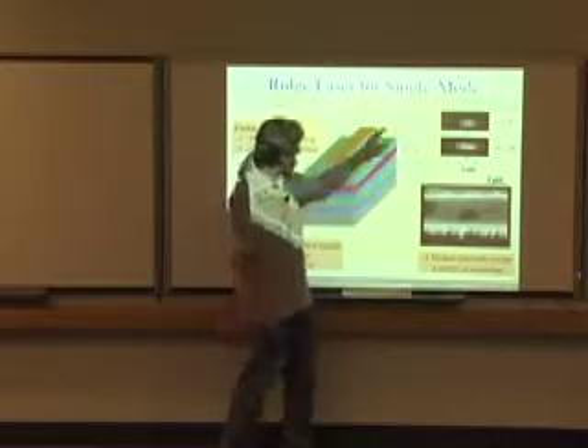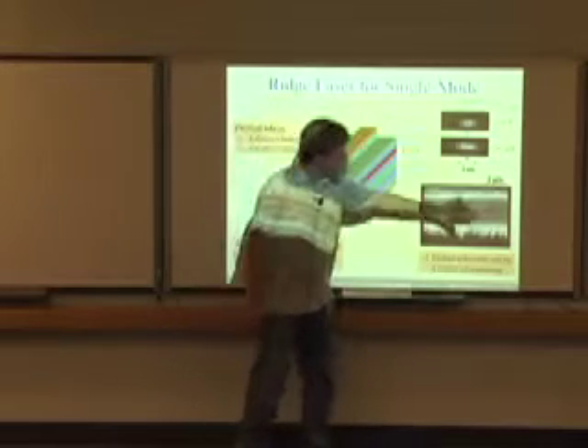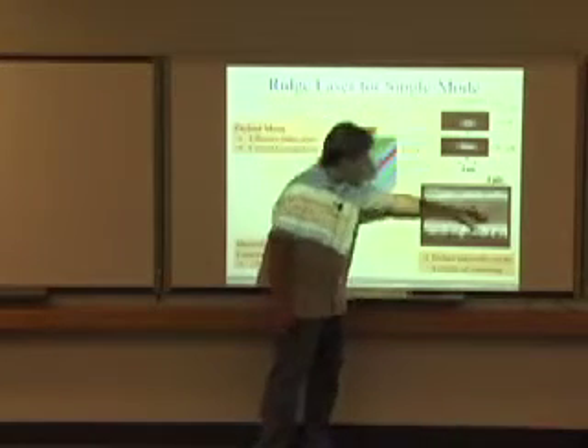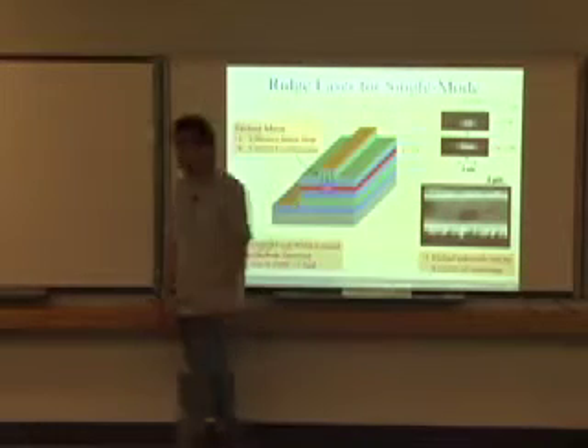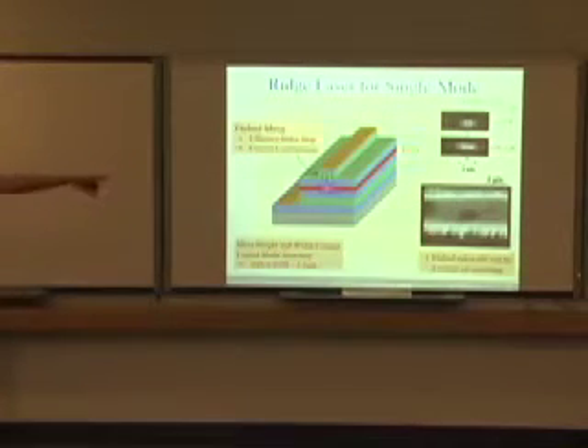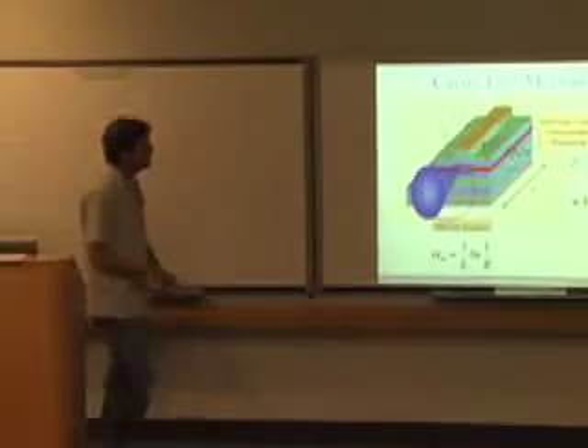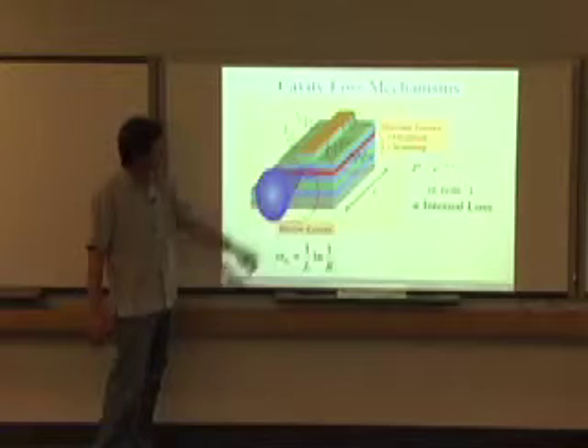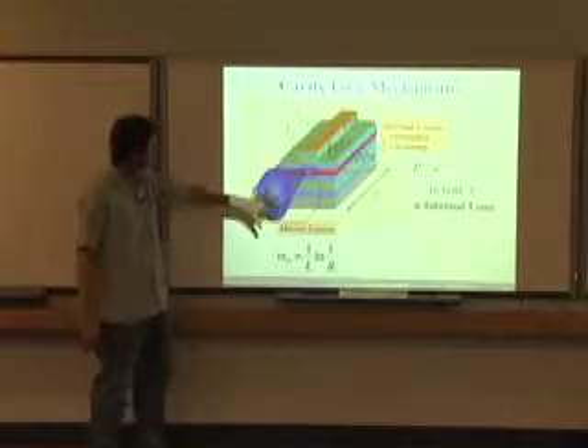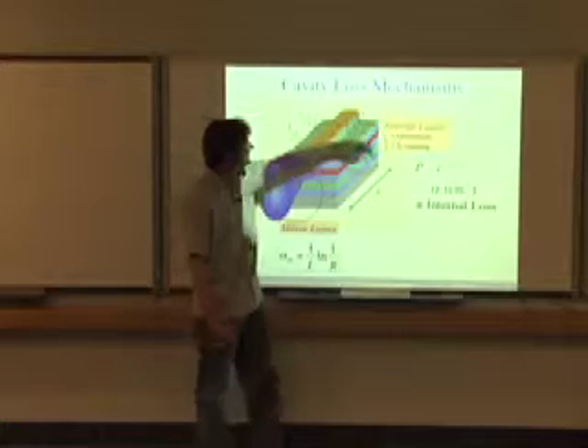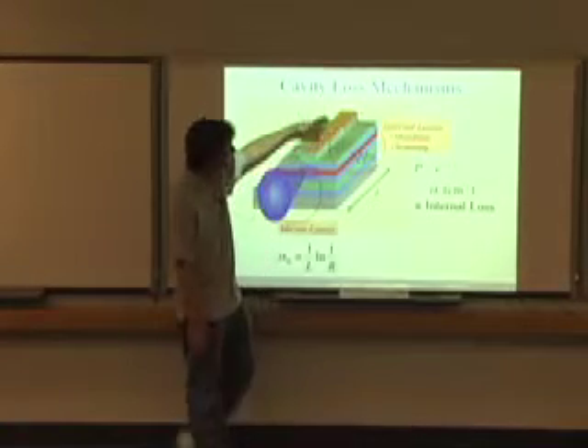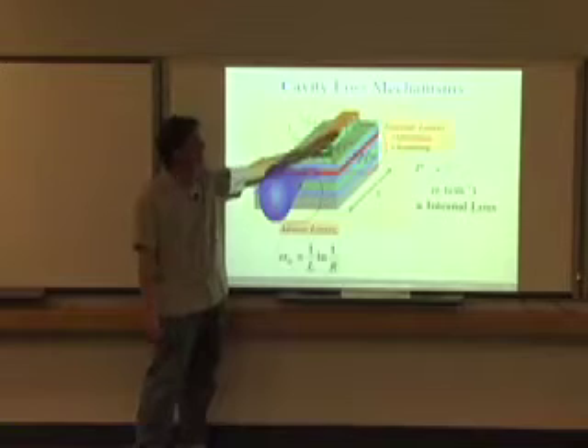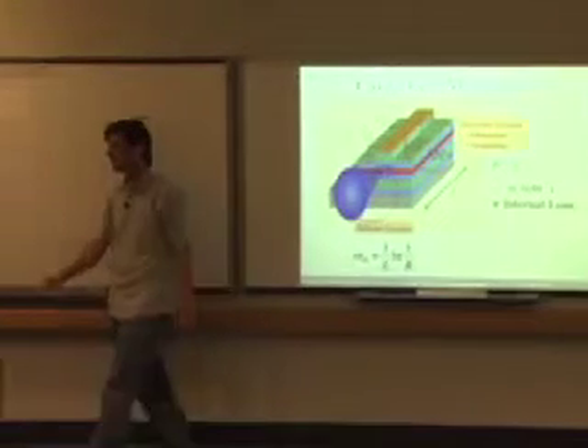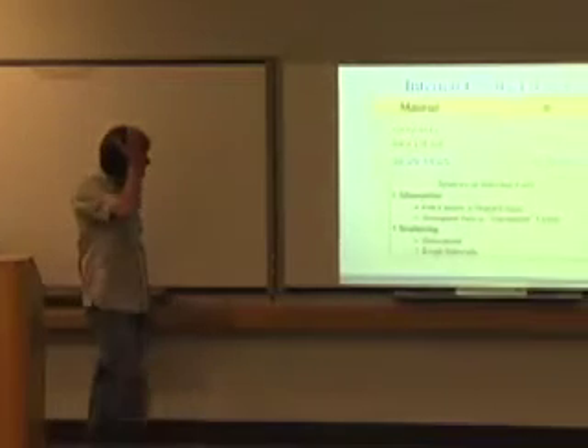And one of the things though is you have to do etching of the sidewalls here. And I just threw in this plot because it's a nice segue to the next thing I'm going to talk about. Sometimes you can have pretty bad sidewalls. This is not from Nakamura's publication. But scattering losses are a big deal. You have to worry about losses, both absorption as well as scattering losses in the laser. Again, it's a different thing than working with LEDs. You have your mirror losses, but with internal losses, you have both absorption and scattering. The scattering can come, of course, from defects that are grown as well as on the sidewalls, but absorption can be a big problem as well, especially in InGaN.